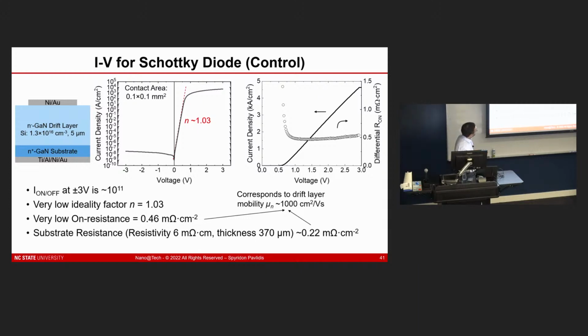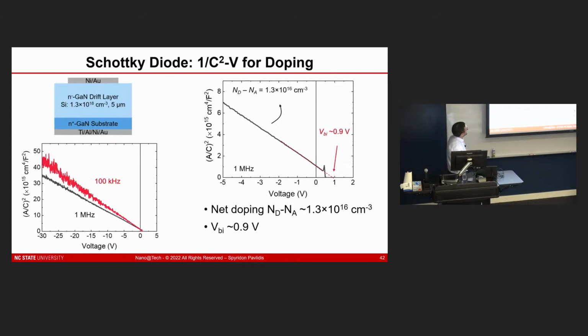And actually, one of the things that's particularly fun for us is we worked through and did some calculations for what we could estimate the mobility in these regions, in the drift region, to be, and we're seeing what we think are very, very high vertical mobilities of near 1,000 centimeters squared per volt second. So this shows that we're getting low doping, 1.3 times 10 to the 16. I have separate CV for that to demonstrate that as well, but I'm not showing it here. But we're also seeing low losses, which are coming from the high mobility in these films as well. So low carbon incorporation basically as well. This is the CV that we have here to demonstrate the 1.3 times 10 to the 16 doping inside here, with the low built-in voltage as well.